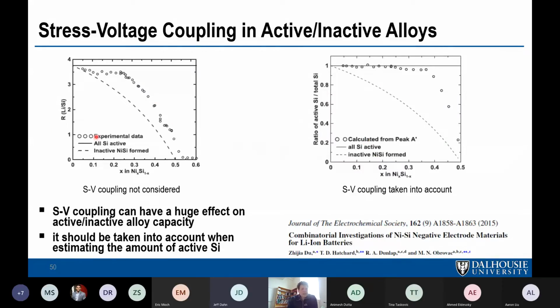And this graph shows you what happens if you don't do that. So this is the amount of lithium per silicon as you add nickel. And you can see the amount of lithium per silicon drops off, the amount of lithium that you can put into the alloy, the lithiation capacity, basically. And it drops off quickly, and it kind of follows this dotted line, like nickel silicide is being formed, which is an inactive phase.